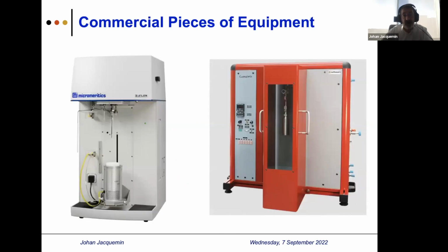published there. Anyway, and just very quickly, because time is running out, we discuss commercial pieces of equipment for porous liquid, because people are mainly motivated to use solid sorbent and to mix or dissolve it, I would say, to make a type III porous liquid. They are really motivated to measure the solid state isotherm from their solid material first. And then different groups modify the porosity method in order to get access to the solubility in liquid, and at different temperatures, not only nitrogen, as displayed here, for example.